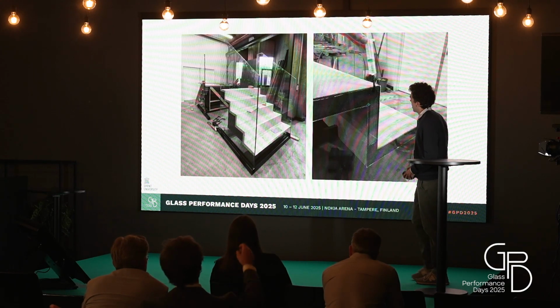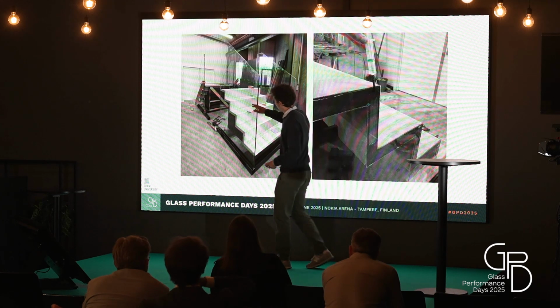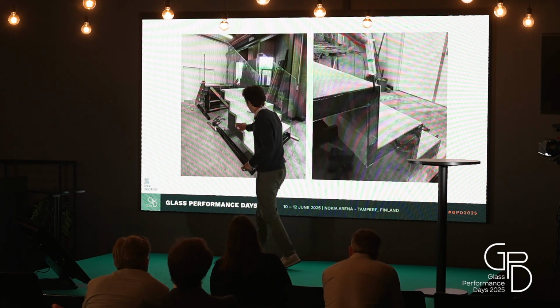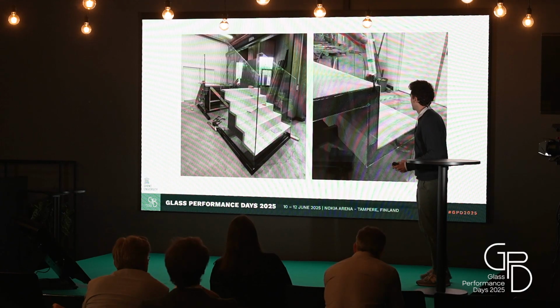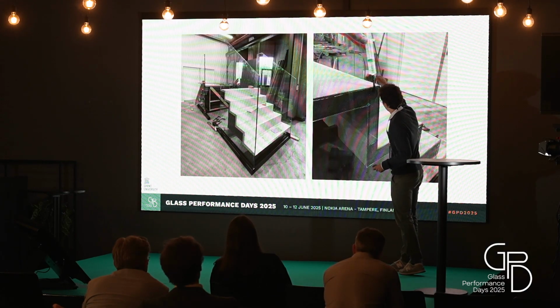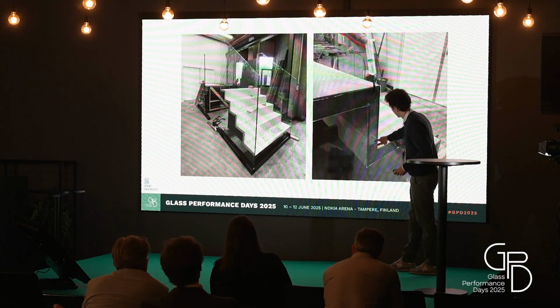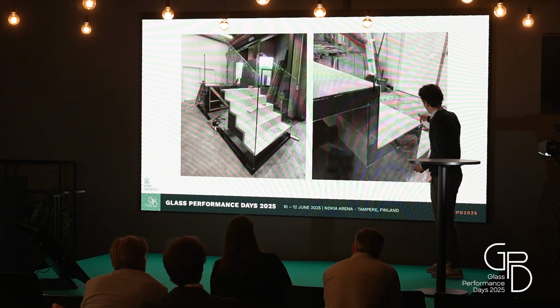For the staircases, we used a similar technique to the full area bond of the panel. Here you can see this line is fully bonded. We firstly taped it off, sealed it with the transparent spacer tape, then placed the glass against it, and then we could fill it from the inside. As you can see here, it fills up from top to bottom. These are all different compartments, so we have to fill them separately.